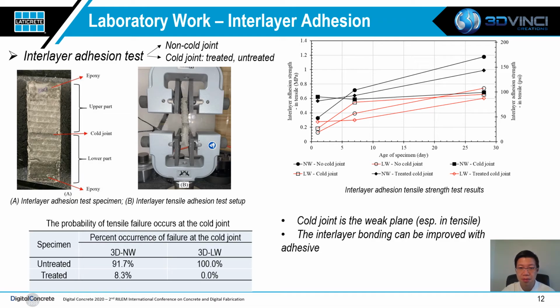When it is treated with an adhesive, a thin layer of adhesive about 1 millimeter thick or less was applied on the top surface of the lower part right before the upper part is printed. The adhesive needs to be fresh to effectively adhere to the layers when we print the upper part specimens. The tensile force is applied perpendicular to the printing direction. The loading rate is 5 mm per minute.